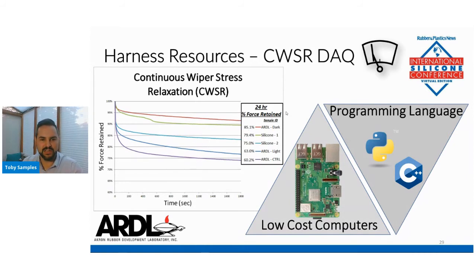The two consumer grade blades were at 75% of the initial retained force and 79% of the initial retained force, which shows me that likely by adding as much as I did of the additive, I'm most likely adversely affecting something that I can't perceive with this simple experiment. In this, I used, again, Python to acquire the data and to acquire these time points of load versus time.